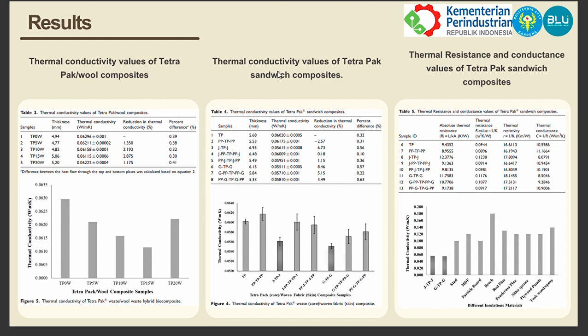And in figure 6, there's the thermal conductivity of sandwich composites, or we can say the effect of skins. First, the glass fabric skins give the best insulation, around 8.5% lower K, followed by jute skin at 6.7% lower. The second is polypropylene layers, which mainly improve bonding, not insulation. And the last, glass fabric reduces heat flow due to its dense structure, while jute offers a natural porosity.